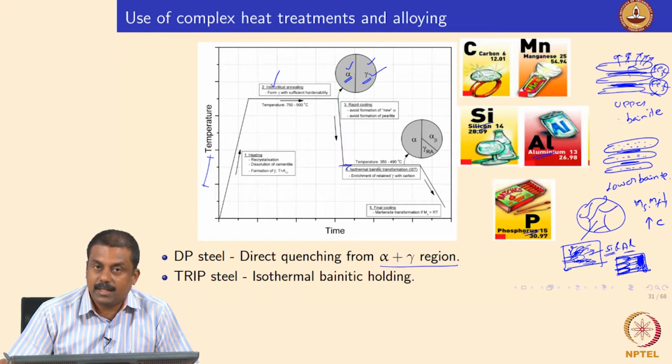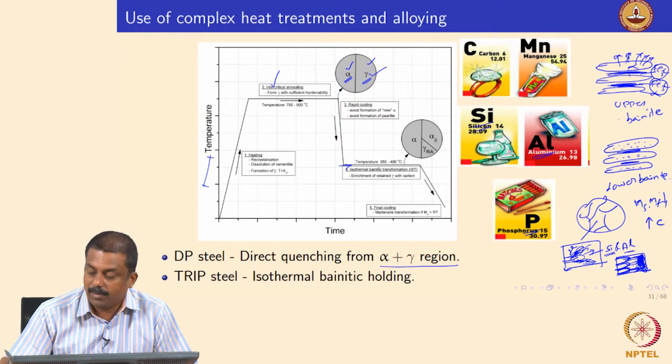You are enriching the austenite, which is untransformed during this transformation, significantly in carbon, right, because if cementite is not nucleated, your untransformed austenite is getting enriched in carbon significantly, isn't it? So, upon sufficient enrichment, there is also an incomplete bainite transformation because the austenite is now stabilized. Because of the partitioning of carbon from the bainitic ferrite, and upon sufficient enrichment, the bainite transformation would not progress, and I will explain some thermodynamics in the next slide.